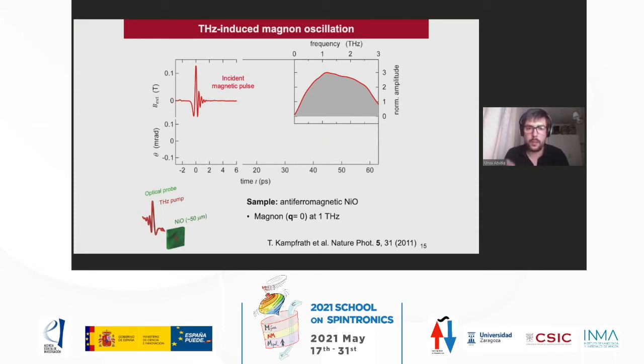This nickel oxide has a magnon at 1 terahertz. The idea was to apply this incident magnetic pulse and see if they could excite dynamics. The dynamics can be measured with an optical probe via the Faraday effect, measuring the transmitted light polarization, which scales with the magnetization.